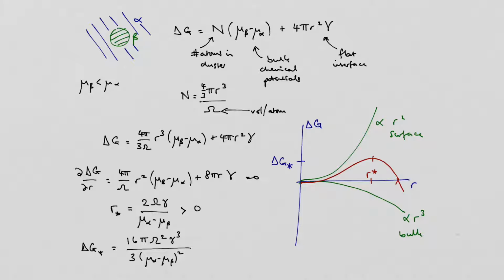But at the point at which you first began that process of separation, there was no energy cost to do that. It was energetically favourable to do that. Whereas when we had to do the nucleation outside the spinodal, you actually still had to go a finite way. You couldn't do it. Nothing was energetically favourable until you made a finite separation into two compositions, at which point there is an interface between them.